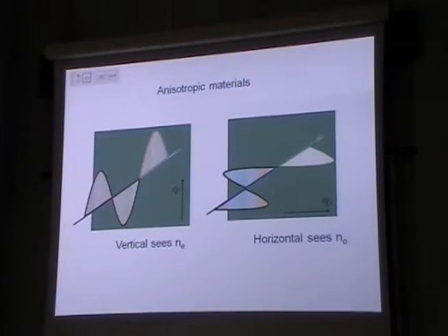This is about a 10mm thick piece of crystal. Therefore, when they come out from the other side, they're effectively leaving the crystal from different places, and therefore I see this displacement from the different polarisation directions passing through the crystal. That's a piece of calcite, not terribly exciting because all it is is a solid. If I replace this with a gooey mush, a liquid crystal, then I can start to manipulate that gooey mush, and I can therefore change that birefringent property.